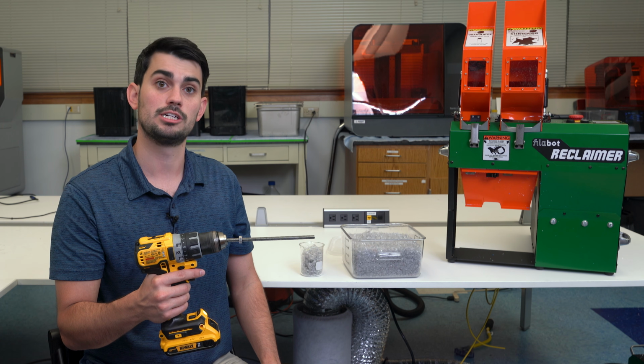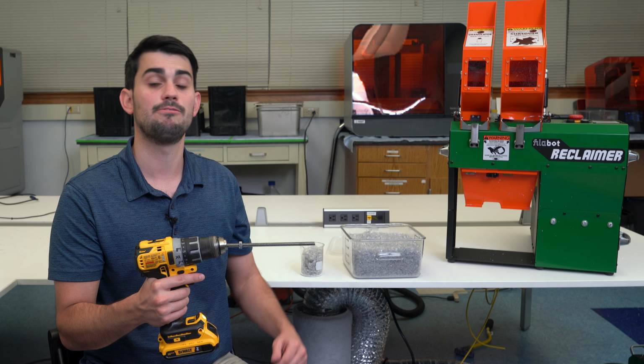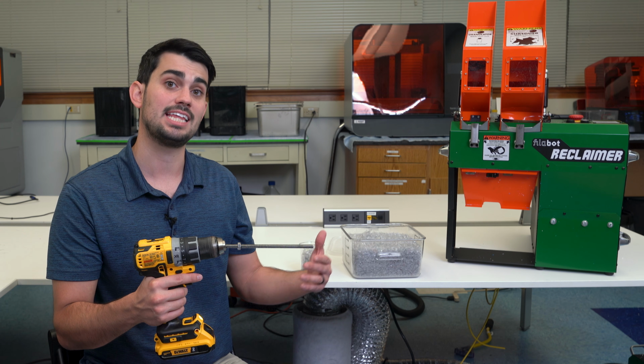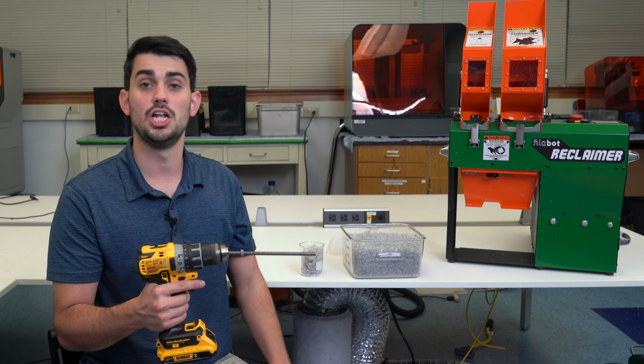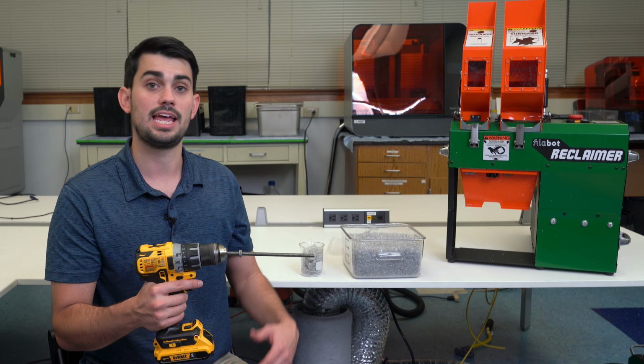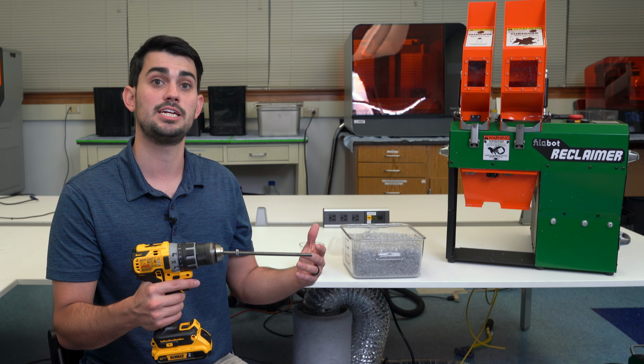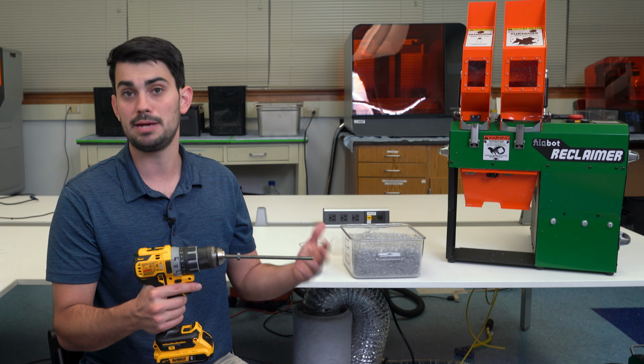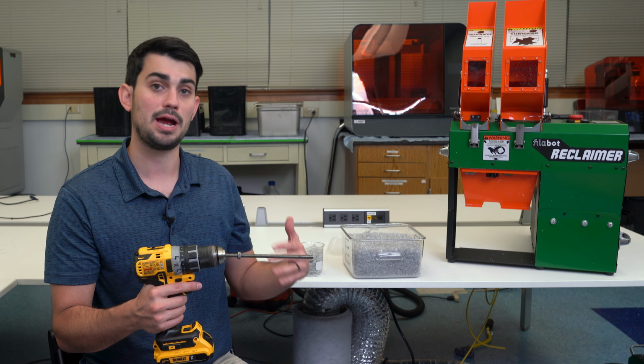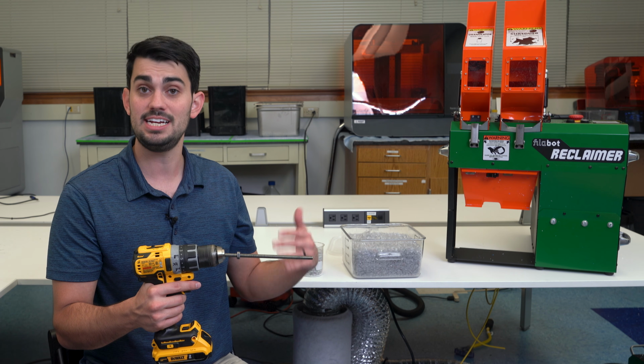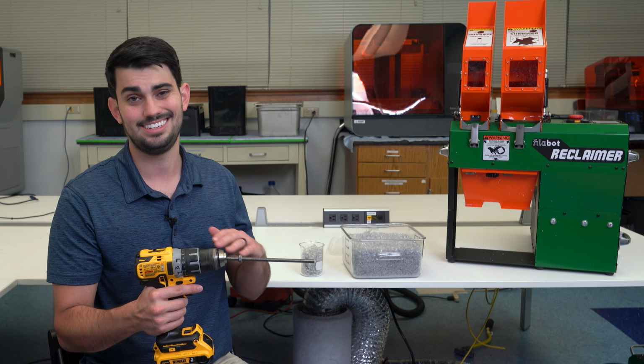In a single screw extruder, we want high friction in the feed section of the screw for conveying the solid plastic material forward along the barrel of the extruder. In the case of low frictional forces, the material will fail to advance and spin with the screw. The heat from the barrel will melt the spinning regrind in the feed section, plugging the extruder. Not good. The low density and thin, smooth shape of the PET flake results in low frictional forces.